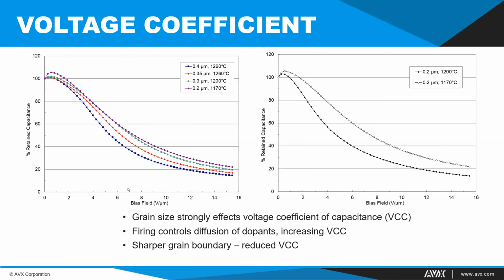Now, given that a lot of materials are used in the vicinity of 5 to 10 volts per micron these days in various applications, you can see that a material can be chosen that has a much better response. We can nearly double the retained capacitance in a device by looking at, say, 6 volts a micron and looking at the 0.4 micron curve versus the 0.3 and the 0.2 curve. So that's an important change. And we can also observe the same thing for the 0.2 micron material. If we fire that material higher and cause the diffusion to take place, we can see that the voltage coefficient of that material tends to become large as we get that peaky behavior that's undesirable as well.